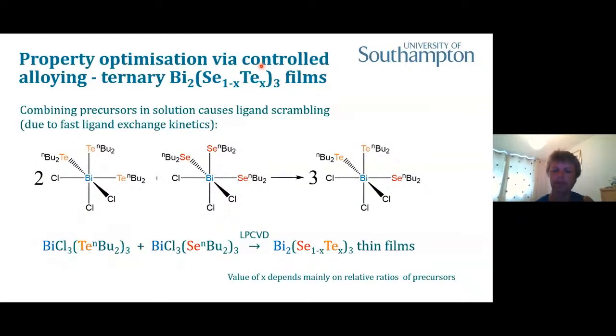So we can produce bismuth telluride and antimony telluride, but one of the key things that we would like to be able to do is optimize these thermoelectric properties by doping in some selenium into the bismuth telluride material, or some antimony into the bismuth telluride, and so on, to create these ternary materials where we get a control of the nanostructure within the interfaces between the crystallites, which has been shown to make a big difference in terms of the measured thermoelectric properties. And the approach we've taken here is again using what I would say is our underpinning chemistry, molecular chemistry, rather than an engineering approach.